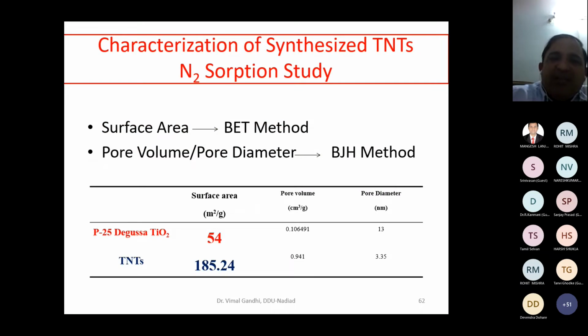Before I go ahead, we compare this titania nanotube with the existing base TiO2 available in the market, and that is Degussa P25, having a surface area of 54 meters squared per gram. It is a very well known fact that Degussa has 50 to 52 meters squared per gram surface area. This is a very well known photocatalytic material available worldwide in the world market. And our synthesized TNT has a surface area increased by roughly 3.5 times, 3.5x, 185 meters squared per gram.